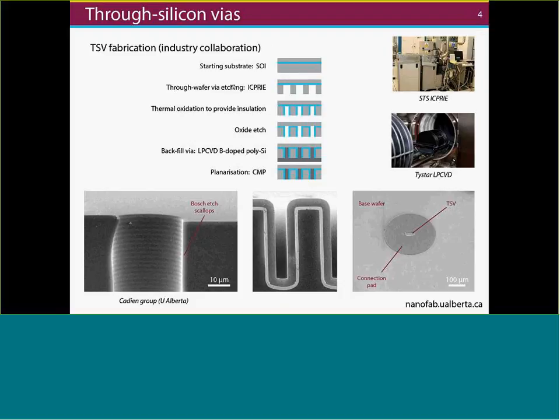You use a deep silicon reactive ion etching Bosch process to etch your vias through, stopping on the buried oxide, do oxidation to provide insulation, and etch through the oxide to provide contact. And then the critical step, we backfill these vias with a boron-doped polysilicon. Now, the wafer is planarized with a mechanical polishing, and now you have your contact between the back of the wafer, each via, and the silicon device layer, which can then be patterned to make whatever sort of device you're interested in, MEMS or what have you.